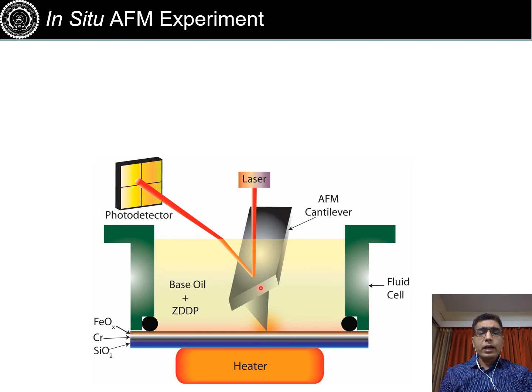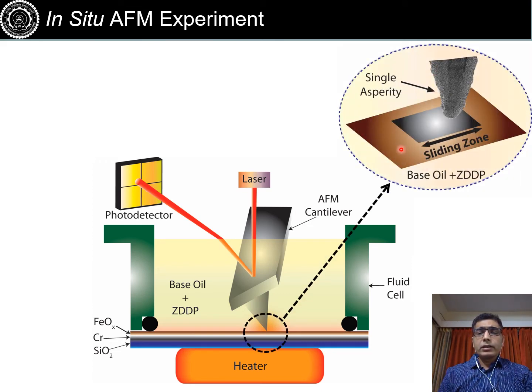And we used a silicon cantilever which is coated with diamond like carbon to provide a high wear resistance to the sharp tip, otherwise it will wear very quickly under high contact pressures. And then we did experiments at a variety of forces, a variety of temperatures, to look at what happens in this kind of environment. So here is the schematic of the experiment. We select a very small region of interest on the sample surface, and we slide the tip at different loads, which will vary the contact pressure between the tip and the sample. And then we do these experiments with different temperatures at different length scales in terms of sliding time, and monitor what happens to the surface.